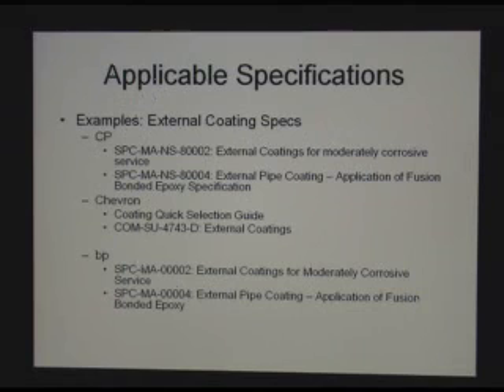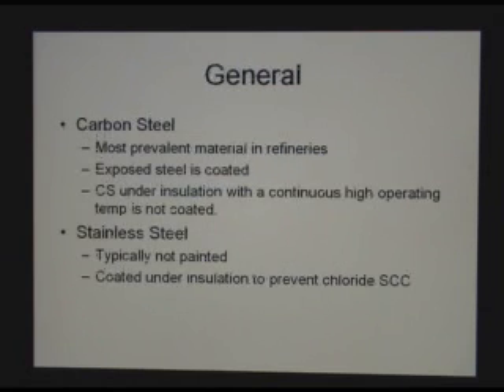Again, we are using our client specification most of the time, but occasionally we have to write our own. So in general, carbon steel is the most used material in refineries. Exposed steel is typically coated. We paint under insulation only if the temperature is low. At high temperature, we don't paint because there shouldn't be any water. Stainless steel is not painted. However, it's painted under insulation to prevent chloride stress corrosion cracking.